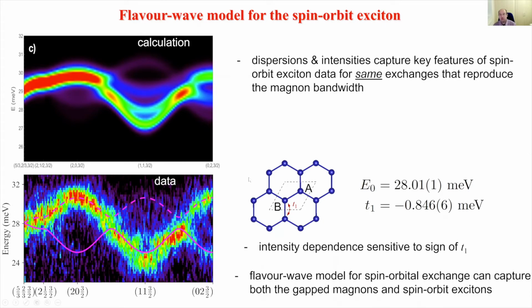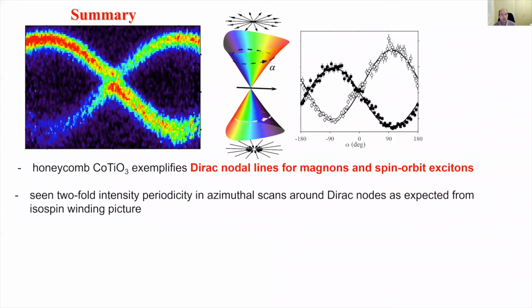So this flavor wave picture with spin-orbital exchange can provide a mechanism to capture within a single framework both the gap magnons and also the spin-orbit excitons. Just to summarize our main results, we've explored the manifestation of linear band touchings in honeycomb cobalt titanate, which exemplifies Dirac nodal lines for both magnons and spin-orbit excitons. We have seen a two-fold periodic intensity modulation in azimuthal scans around the Dirac nodes, as expected from this isospin winding picture.